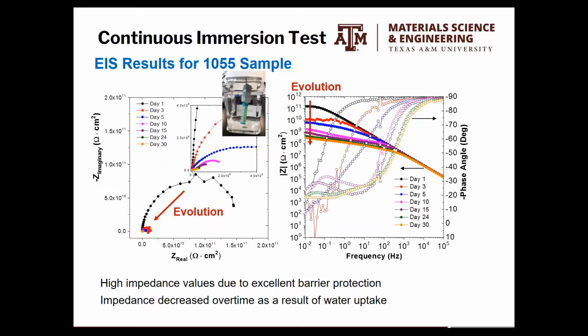So 1055 is a system that contains the rebar, the plain, flat steel, I call it flat steel, and the black steel. I think that's the jargon in civil engineering, and the black steel with the galvanized layer and also epoxy. The only thing that I want to highlight in this representation is that the impedance you see is 10 to the 11, previously it was 10 to the 5. And what that means I'm going to explain later.